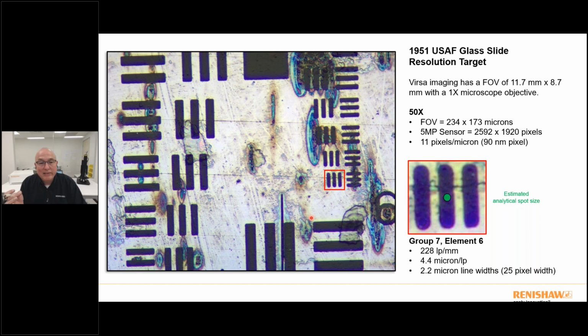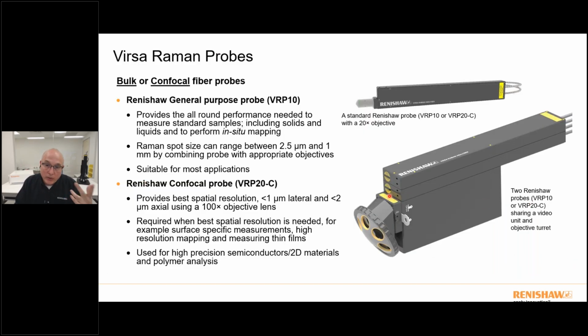So you can very easily position these probes on top of very small features and be able to acquire spectra confocally on top of those features as well. So that's one big advantage as well. We deliver 2 different types of probes. One is going to be intended primarily for bulk analysis. That's the VRP10 or Virsa Raman probe. And then we have another one which is intended primarily for confocal analysis, and that's the 20. And then again, you can still have the video option on these. You'll want to use the VRP20 when doing high confocal work. So if you're thinking about thin films and things like that, then that's a good application for it. Otherwise, the standard bulk probe will do really well on most measurements here.